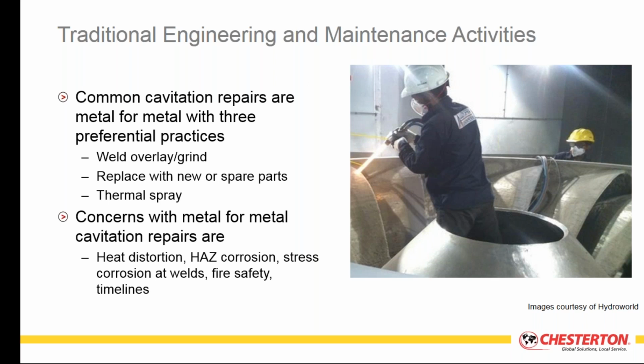We're going to be concerned about the heat-affected zone, the actual weld pool and the region directly adjacent to the weld pool. Those are areas that are more prone to corrosion, so we need to be quite confident that the weld has been properly inspected and verified as smooth and clean. We do that so we can eliminate the effect of stress corrosion at the welds.